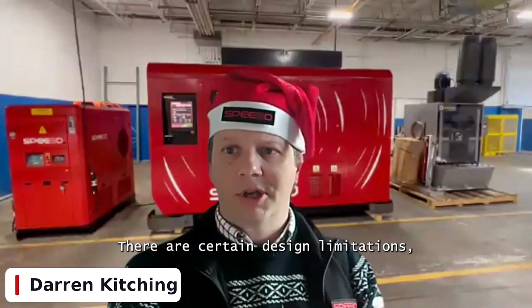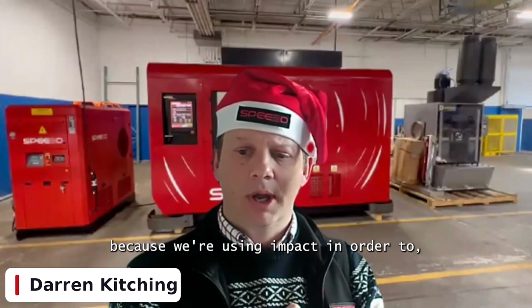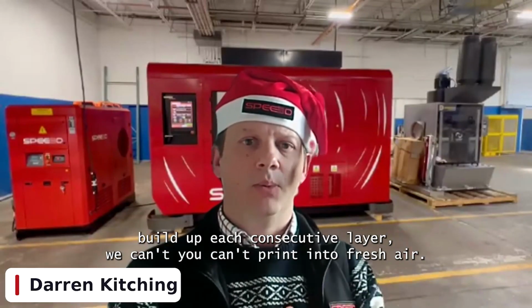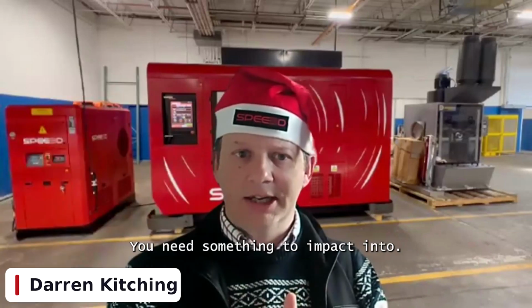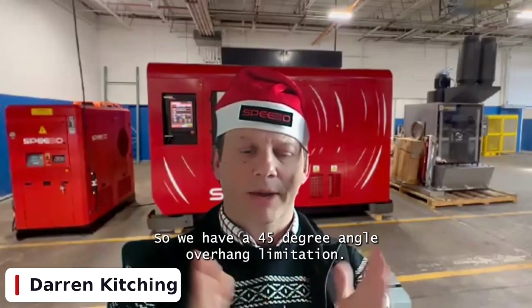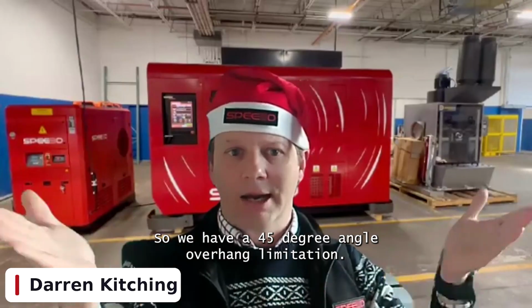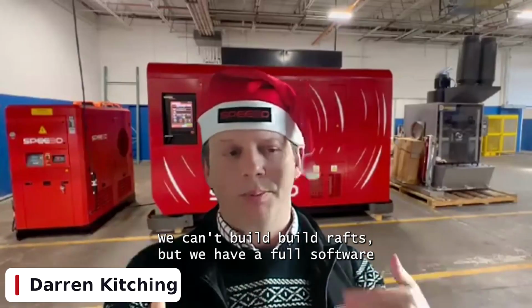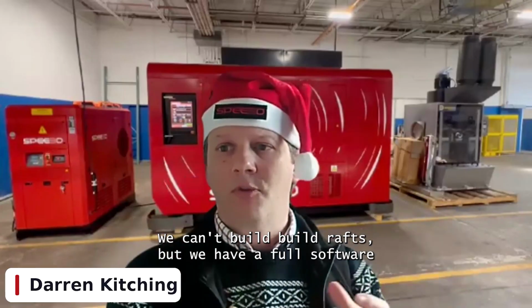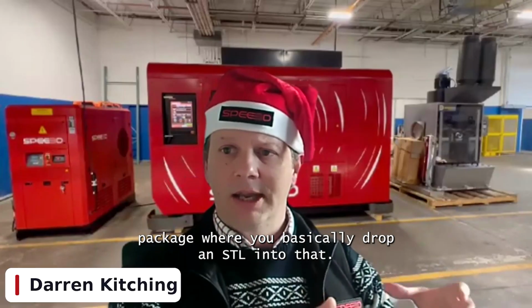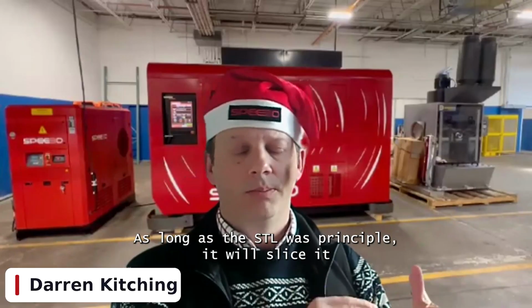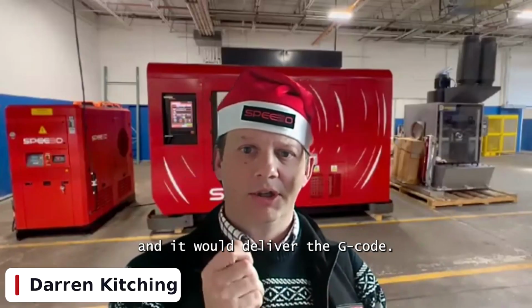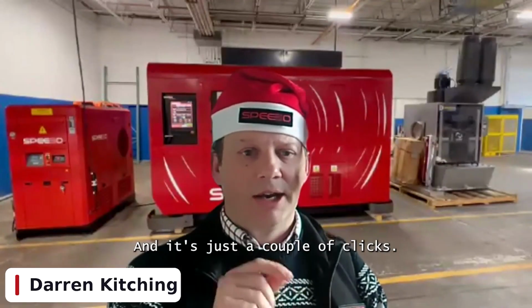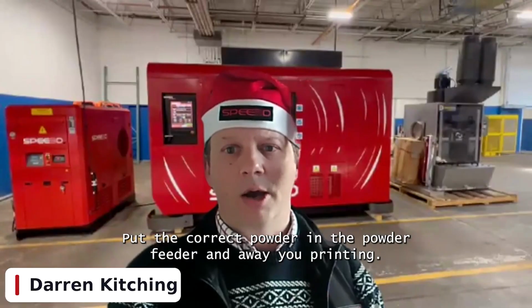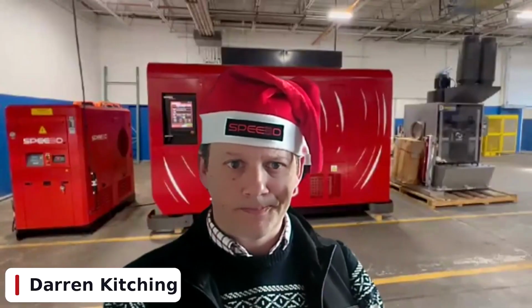There are certain design limitations because we're using impact in order to build up each consecutive layer. You can't print into fresh air. You need something to impact into. So we have a 45-degree angle overhang limitation. You can build rafts in there, but we have a full software package where you basically drop an STL into that. As long as the STL is printable, it will slice it and it will deliver the G-code. You take that G-code, put it on the printer behind me, and it's just a couple of clicks, put the correct powder in the powder feeder, and away you're printing.